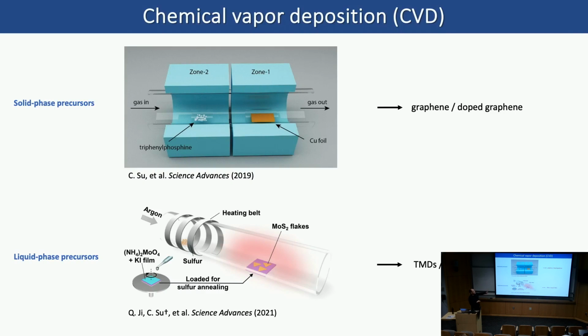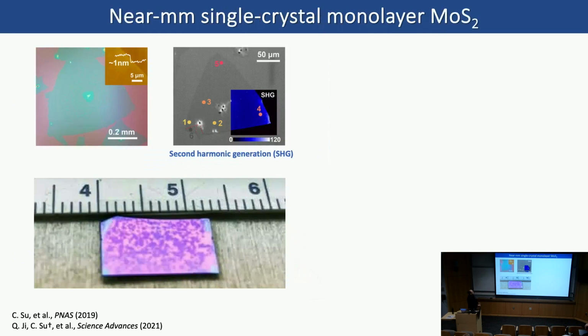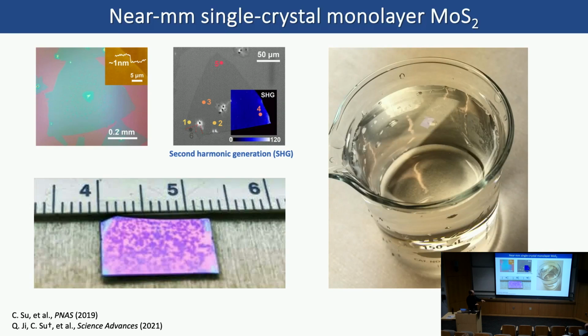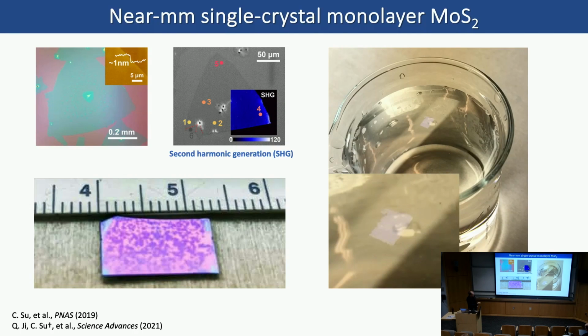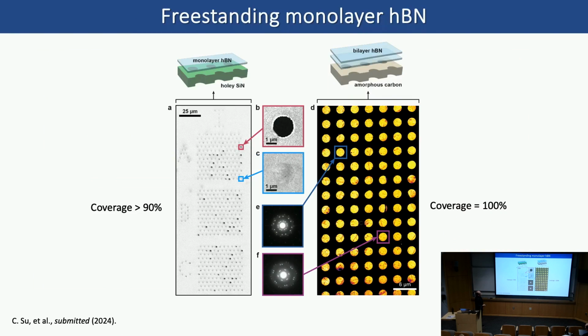Okay, so I'm just trying to show you how we got those 2D materials. Like CVD, we could grow using solid phase precursors, liquid phase precursors. We could grow all kinds of 2D material. We could get very big single crystal monolayer material. So these flakes, if you look at them with your naked eye, you could see a single flake, which is 1 monolayer thick. So they're pretty big. And you could also float them on water. So this is a piece of monolayer MoS2 floating on water, which you could use a tweezer to poke around, which is actually kind of fun. When you imagine it's a monolayer, a single atom layer, it's quite fun to play with.